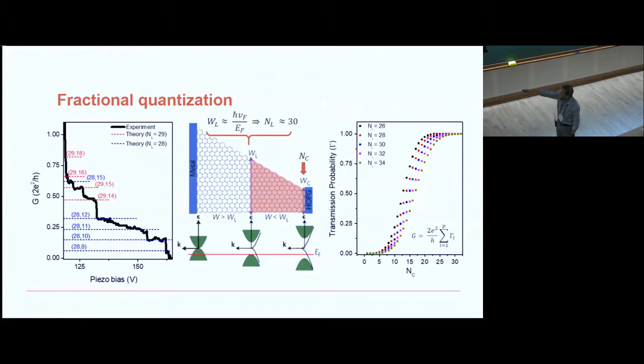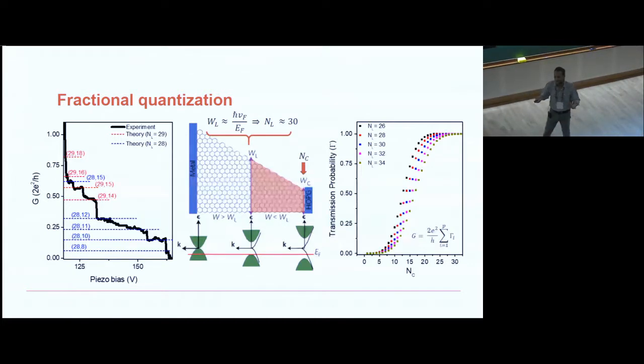Conductance decreasing means this is the one side which is a large tip, and this is the substrate. I'm creating a bridge which is a tapered 30-degree bridge between the two sides. The width matters, absolutely. It doesn't matter only in semi-infinite graphene. But the moment I make the graphene channel less than 5 nanometer or 10 nanometer, the wave function of the edges actually goes deep into the graphene in this direction, and it starts seeing the other edge. And that's when the wave function starts reflecting back.